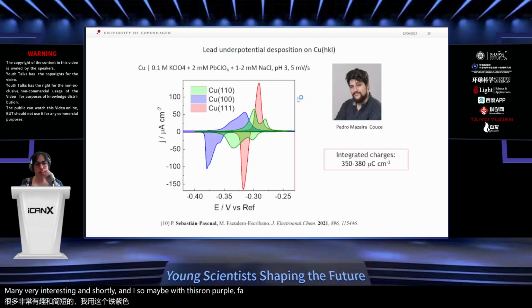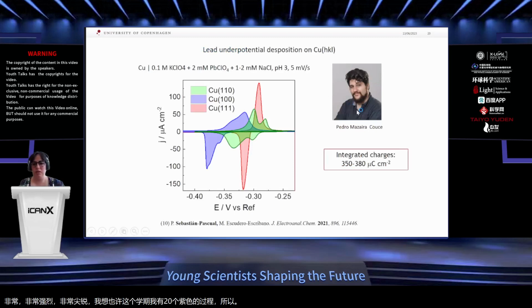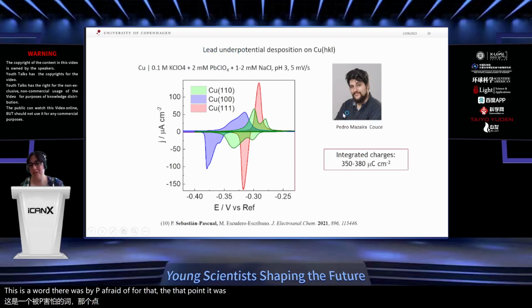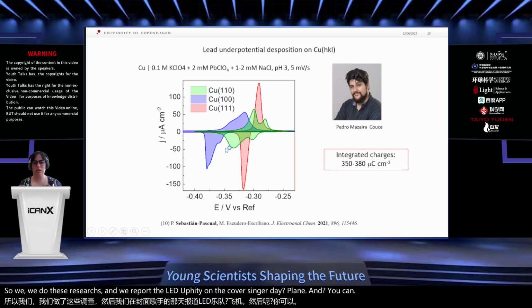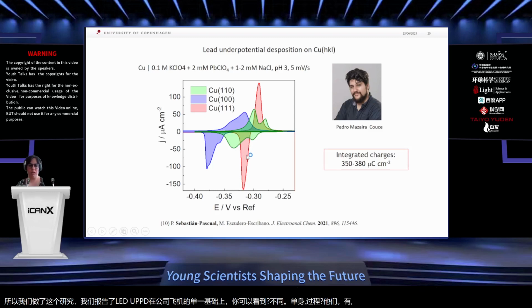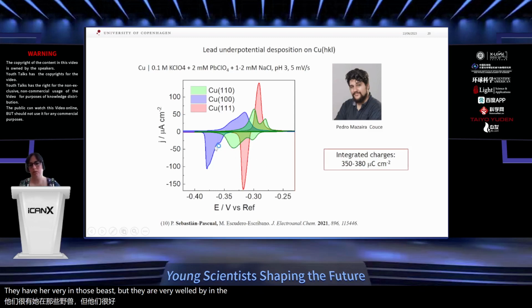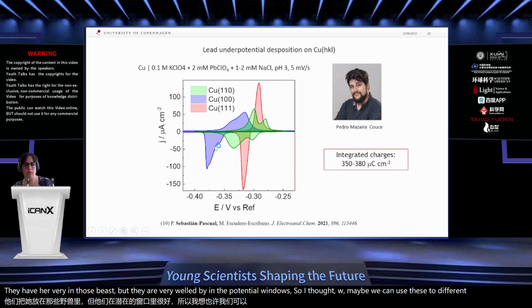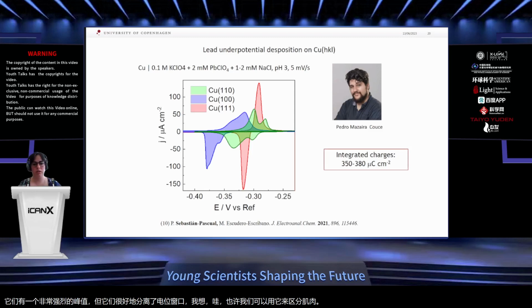So then, this is a work that was done by Pedro Mazaira Couce, who at that point was a student of ours. So we did this research and we reported the LUPD on the copper single basal planes, and you can see that the different single facets have very intense peaks, but they are very well separated in the potential window. So I thought, wow, maybe we can use this to differentiate facets in polycrystalline surfaces.